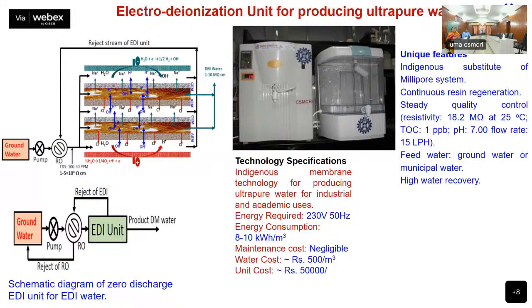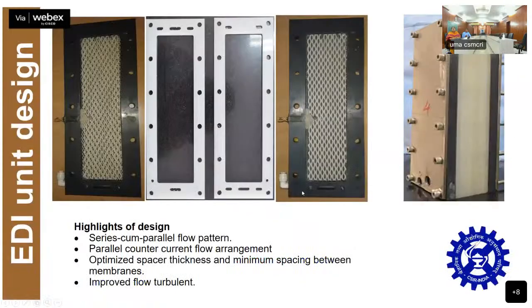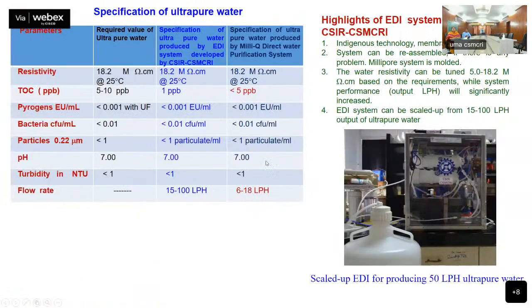So these interpolymer-based ion exchange membranes are very useful. In between the ion exchange membranes, mixed bed resins are used. We have compared the performance of the unit with a commercial unit. Our water specification is as per Millipore, and we have also developed a system with a capacity of 50 liters per hour of ultra-pure water production.